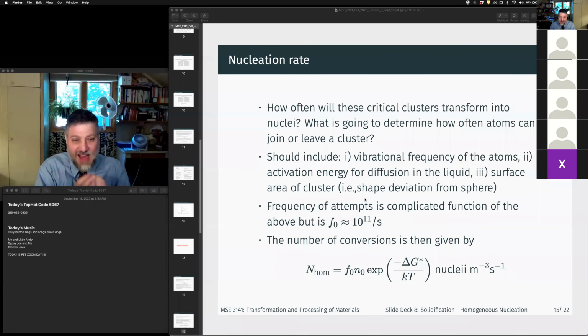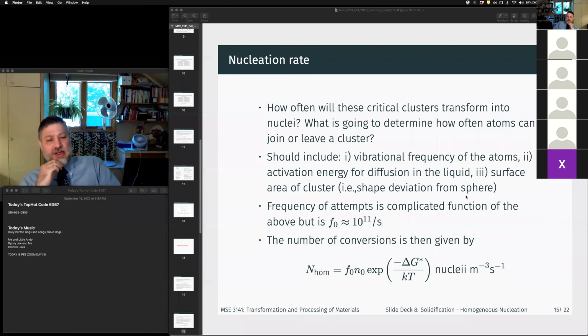The clusters themselves are not perfect spheres. We model them as perfect spheres, but in reality, they have to take some kind of shape based on the anisotropic energies associated with bonding, right? So in a metal, a sphere is not a bad assumption, but in an ionic or covalent system where you have strong directional interactions, you're highly unlikely to make a spherical nucleus. But anyway, the frequency of attempts ends up being a complicated function, but it turns out it's about 10 to the 11th per second, right? Which is fairly similar to the vibrational frequency of the atoms, right? And when I say fairly similar, I mean within an order of magnitude or two.